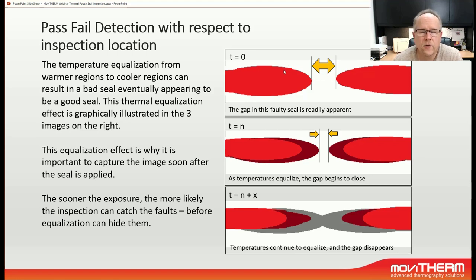And if my camera location has been selected properly, I would have no issues detecting this fault because I could see, hey, here's a discontinuity of the energy, therefore that's a fault. Waiting a little bit longer, that energy will slowly spread from the hotter regions to the colder regions. Since the fault is cold, we essentially have a bleed into this area, and further down the line, if I placed the camera in the wrong location and waited too long for the inspection, I may miss the faulty seal because the hot regions have completely bled into the cold regions, and my system will just deem this as an okay seal, although it is not. So this is very important to understand, and it's very important to have the right knowledge about what happens with this particular application and also where to place the camera with respect to where the heat is being applied.